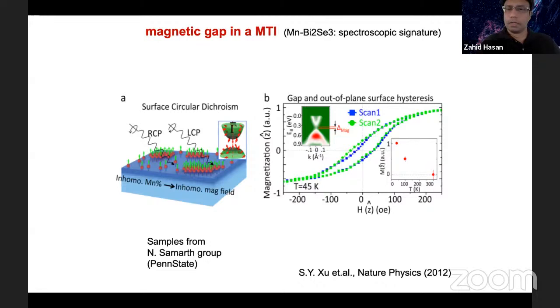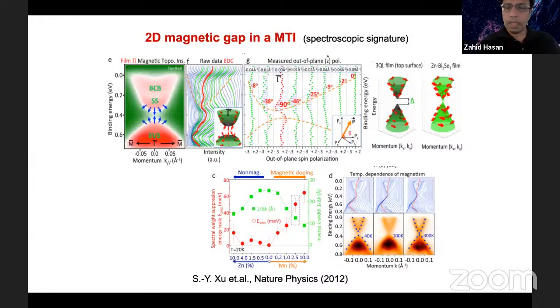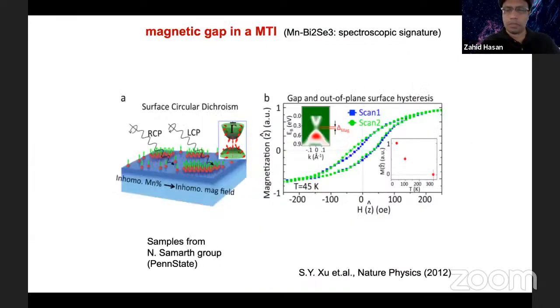So how do we address that experimentally? One thing we applied is to look at the surface circular dichroism with different helicity photons and see whether the surface is dichroic. We can also track magnetization on the surface and see whether the massive Dirac fermion state, or the gap opening we see, is correlated with that. Another check would be to see, when magnetization disappears, whether the gap closes, so you recover the Dirac fermion or not. It turned out even those systematics would not uniquely identify a topological gap.